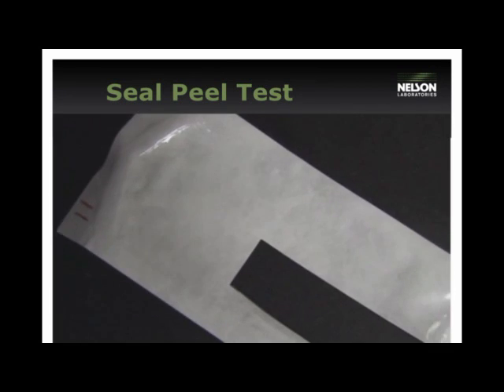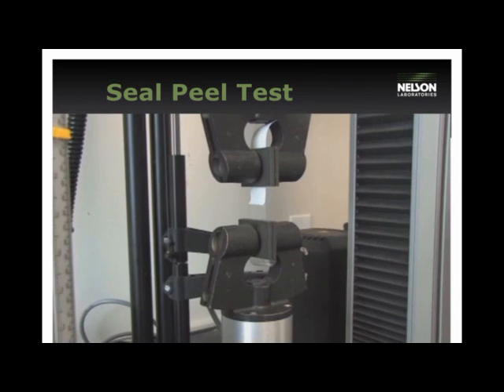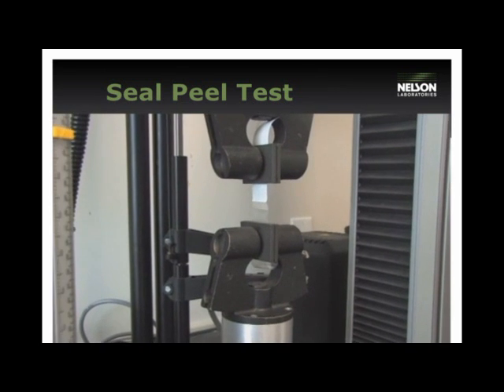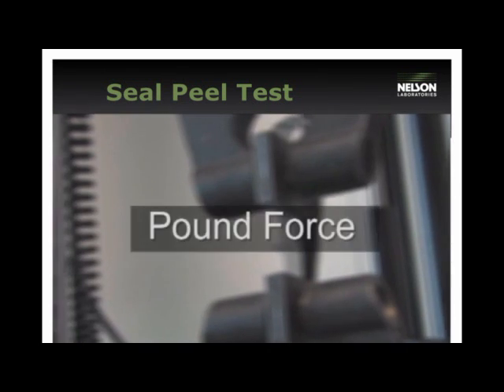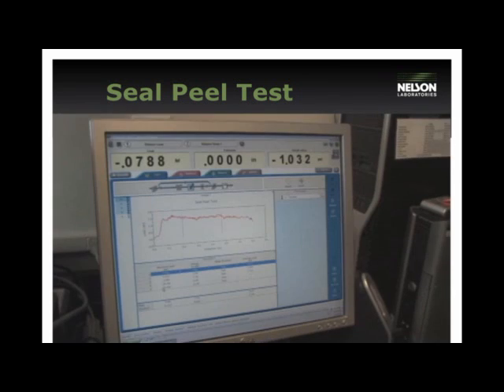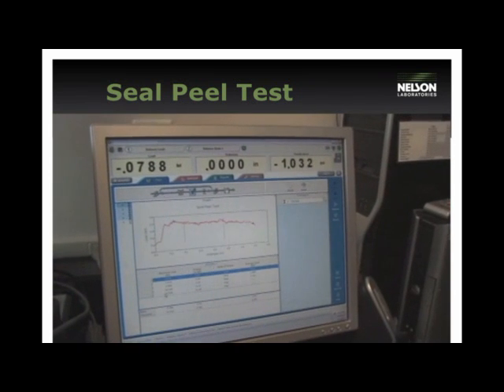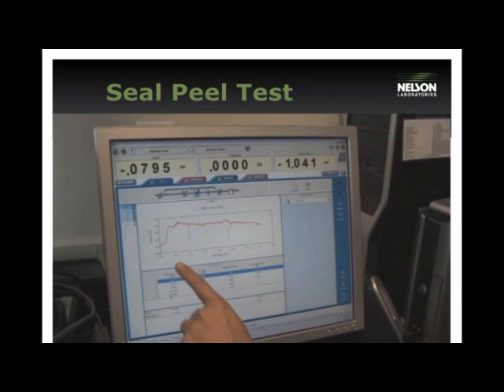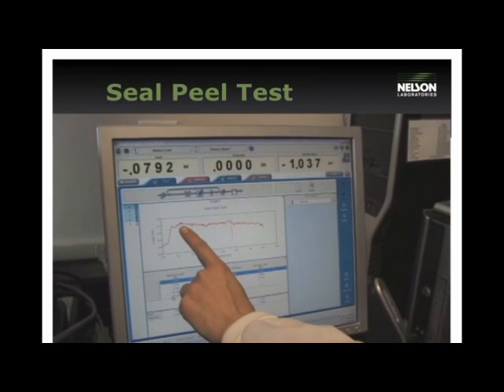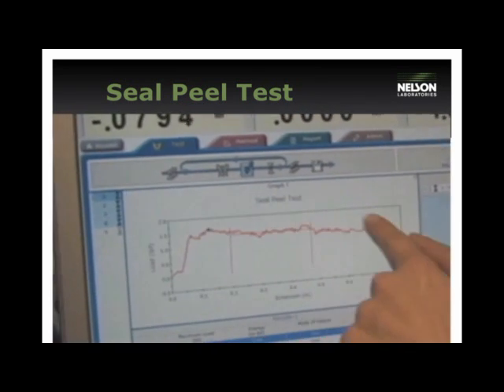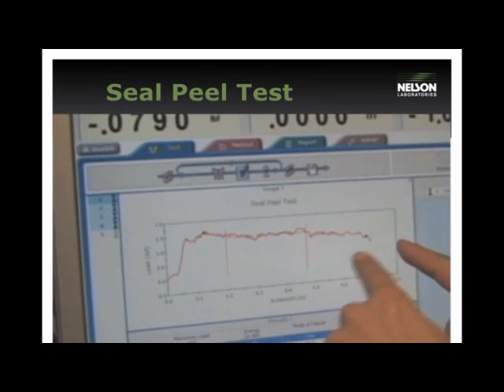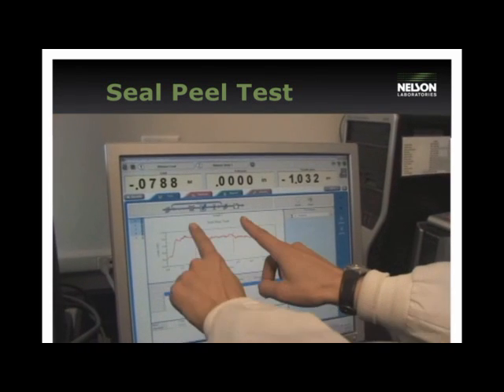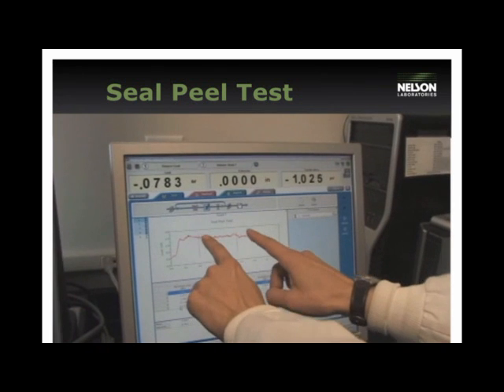Seal peel is a strength test. A 1-inch section of seal is cut from a package and pulled apart on a tensile testing machine. The force required to peel is recorded in pound force. This is a graph of a typical peel. The maximum peel is the highest force value. The energy is the area under the curve. The average peel is the average from the middle of the curve.